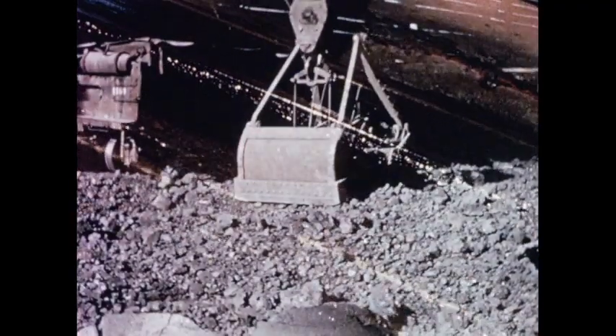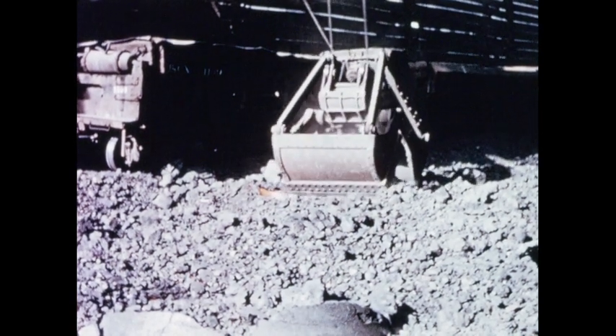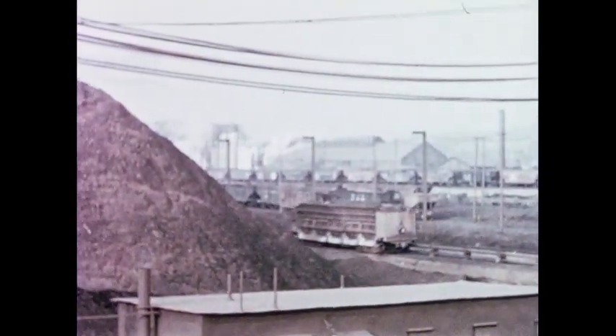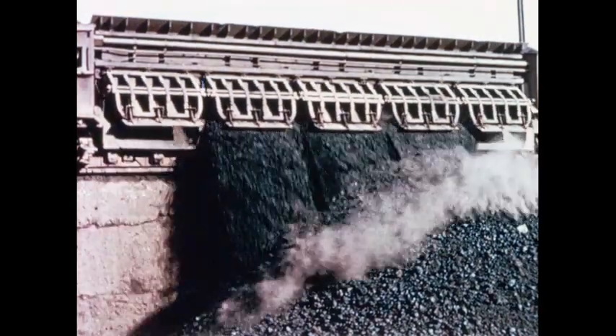Before T1, 9% of all delays on a slabbing mill were caused by failure of the chain on this scrap butt conveyor. Butt ends used to twist and break the links. Since the installation of T1 links, the mill has had practically no downtime due to link failure. The steel lips in this bucket, operating in temperatures up to 600 degrees Fahrenheit, used to last 1 month. The new T1 steel lips lasted over 11 months. The pockets of this transfer car were subject to such abrasive wear that yearly replacement was required. But with T1 steel, 2 years passed and replacement still seemed far off.